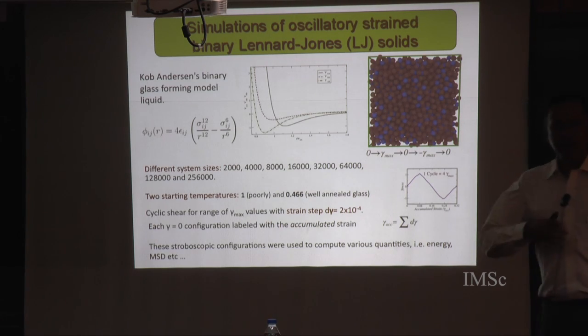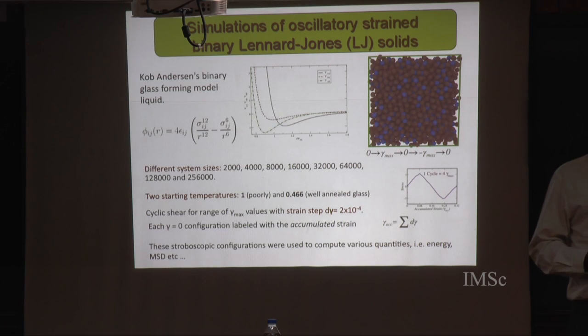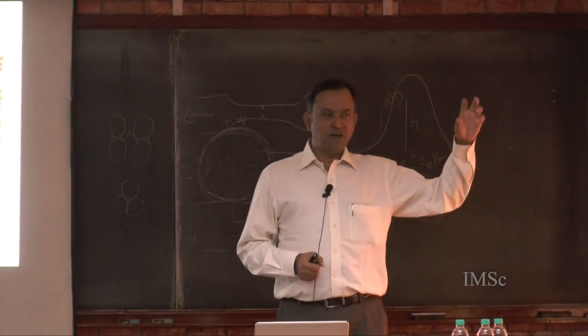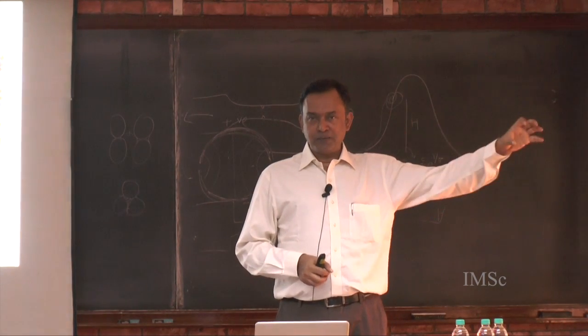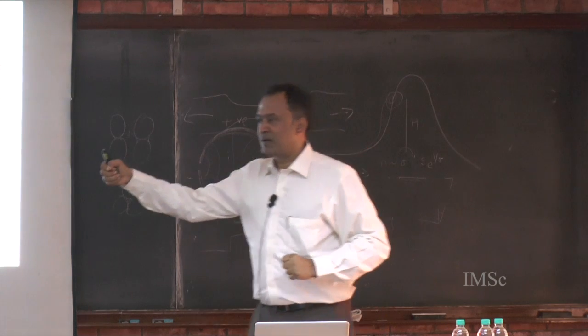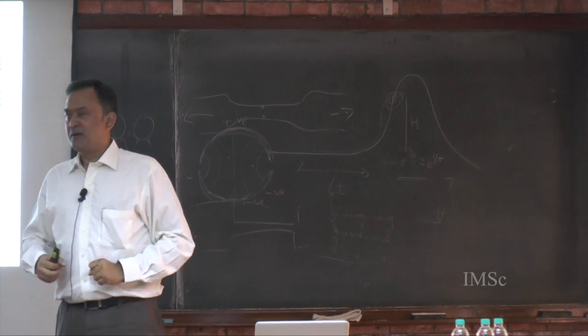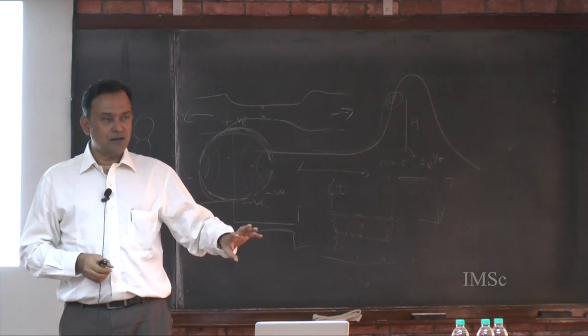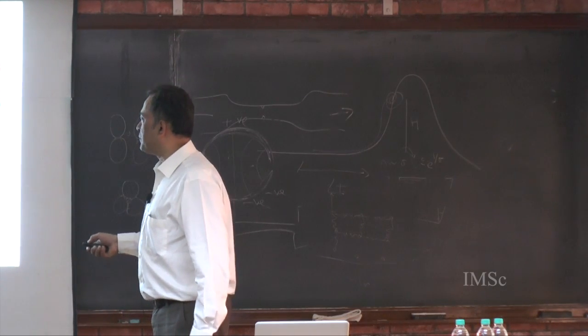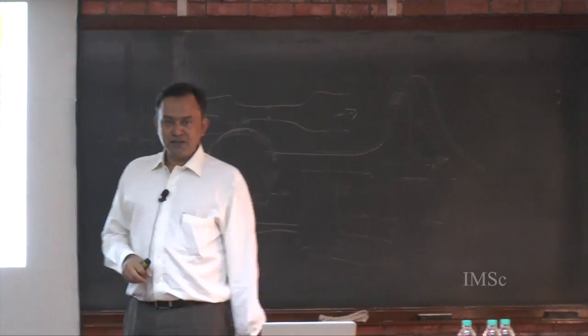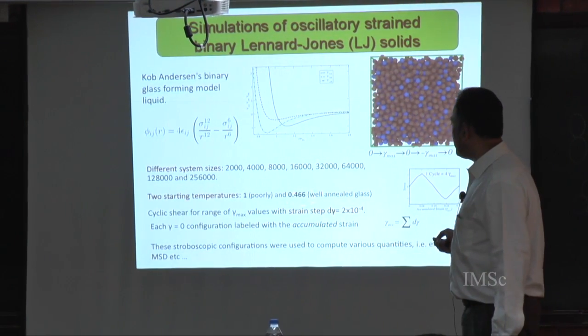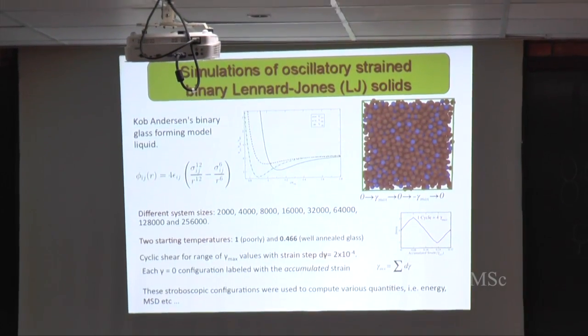In everything I'm going to tell you, I'm going to look at two samples, so to speak. We're going to look at glasses prepared by an instantaneous quench of a liquid that was in equilibrium at a high temperature, and an instantaneous quench of a liquid in equilibrium at a low temperature. The former I'll call a poorly annealed glass, labeled by this temperature number of 1 in reduced units, and the well annealed glass is labeled by this temperature of 0.466 in reduced units.